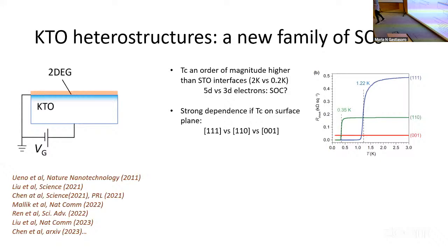The next thing I wanted to mention is, while we were thinking about these things, people in the labs kept designing new things, and as usual, reducing dimensionality is one of the things that people do. So in this case, they did heterostructures: they sandwiched one of these oxides which are close to this ferroelectric instability with different things. And there is a two-dimensional electron gas. You can imagine that up here there is something else, and that something else can be very different. The end result is the same: you get a two-dimensional electron gas.